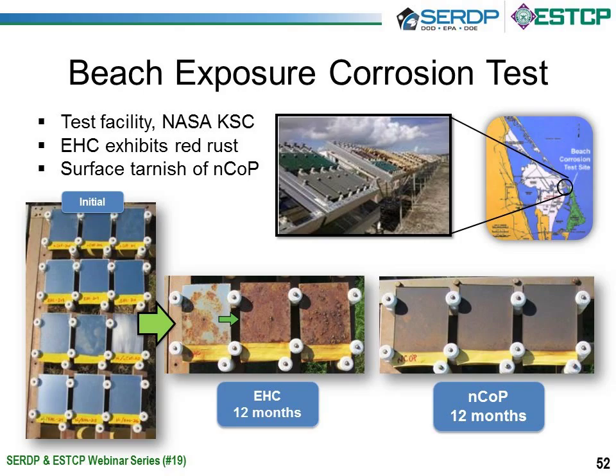This is the chrome-plated coupons after 12 months, and this is the nanostructured cobalt phosphorus coupon set after 12 months. You can witness here that there is some light oxidation. So we returned these samples back to our laboratory and had further analysis performed that we'll discuss later in the presentation.